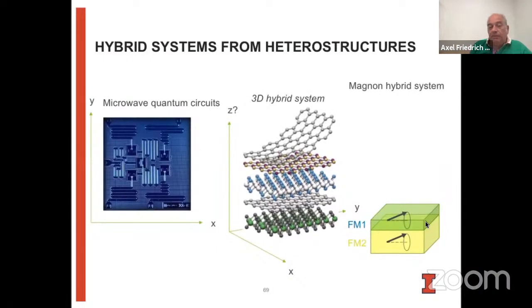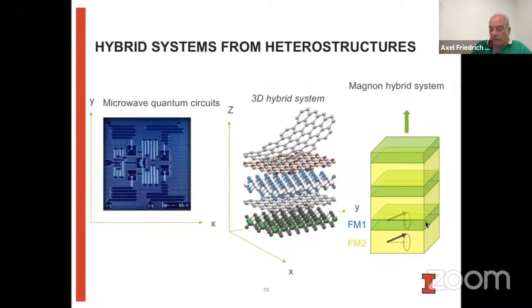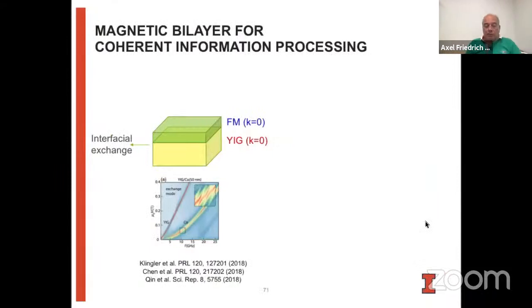But magnetic systems actually may offer a nice opportunity here, because the magnons in the magnetic system are naturally, of course, confined to the magnetic material where they are. And so that may allow you to come up with a structure that becomes much more three-dimensional. And so you can stack two magnetic layers on top of each other, or you can make a much more complicated structure where then the microwave signal also can translate in the thickness of the film and do some other kind of functionality. Now, with this in mind, we then wanted to see, okay, how can we transmit coherent information from one layer to the next?